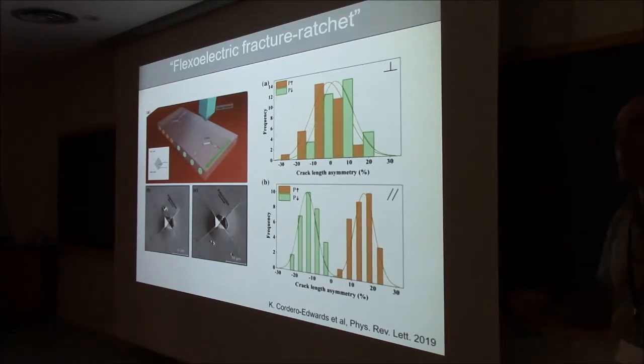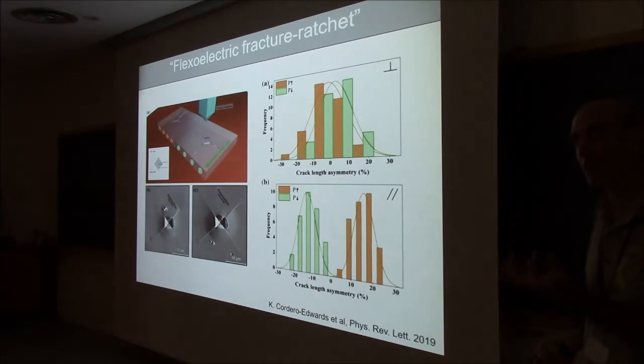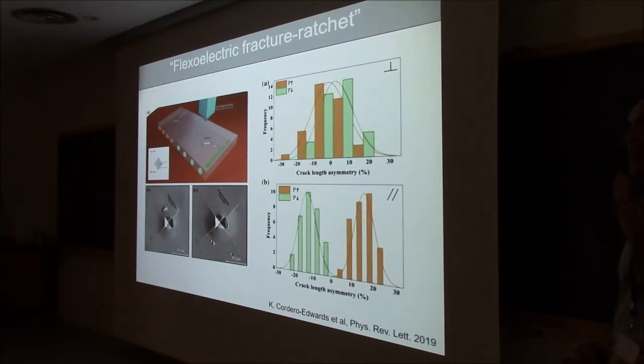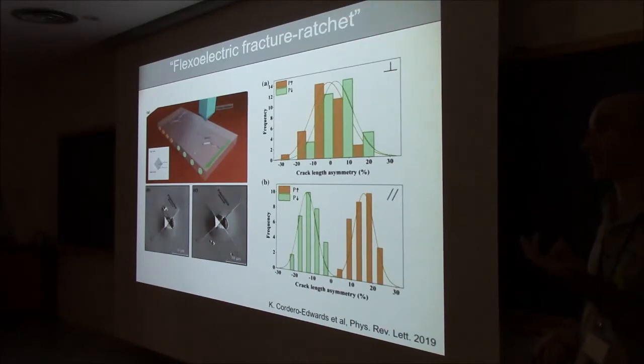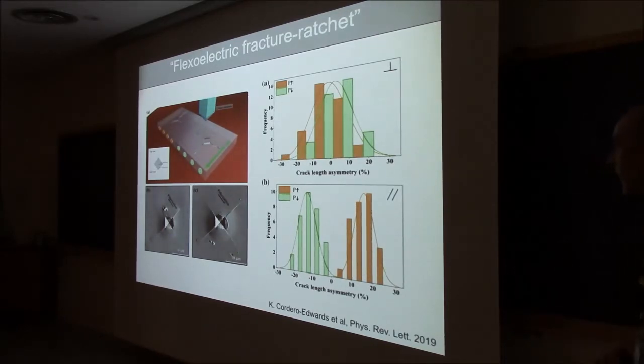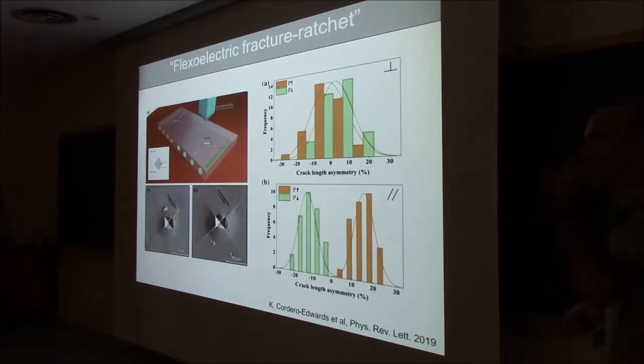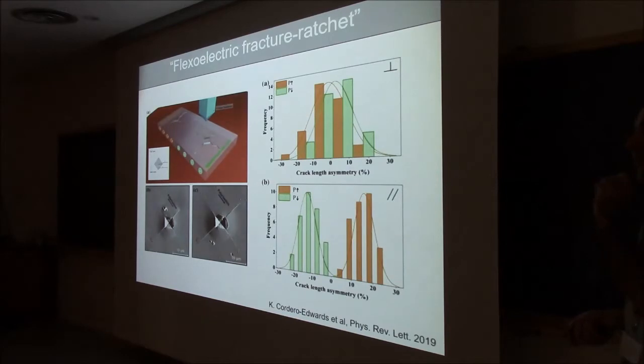And this is, I think, also quite profound, because in mechanics you always assume that everything is centrosymmetric, because as I was saying, stress and strain, all these things are given by even particle tensors. Once you have strain gradients, you can no longer assume that, so you can never assume that your fracture pattern is going to be symmetric in a polar material. Whether this is useful or not remains to be seen. It does mean, though, that how much your ferroelectric ceramic fatigues or cracks depends on the polarity.